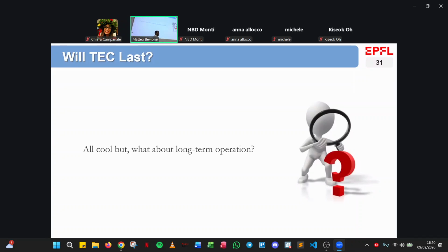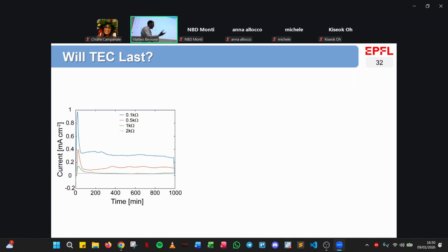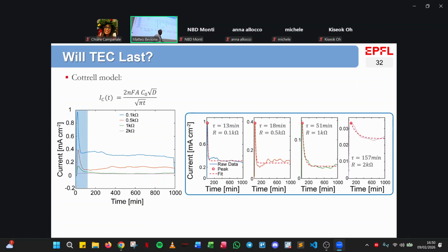what I said at the beginning was, you need to have something that works for a long time. This is not just a one-time energy delivery and that's it. You need something that lasts for a long time. So what about the long operation? What I did was fundamentally to take this thermoelectrochemical cell, attach a resistance to it, and then measure the current. And as you can see, at first we have a very high peak, and then a relaxation in time. And the relaxation depends on the resistance you are applying, indicating that the higher the resistance, the slower is the depletion of the species close to the electrode, and the slower you get to a stable condition where the diffusion matches the reaction at the electrodes.